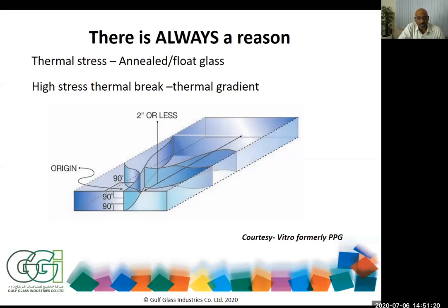Now, in service conditions, what we have seen is any temperature difference between the edge and the center of the glass, about 40 degrees centigrade, can create such high stress breakages. You don't have to do thermal stress analysis on tempered glass or heat strengthened glass, because tempered and heat strengthened glass can take a temperature difference between the edge to the center of approximately 250 degrees centigrade, which is never going to happen on a building.